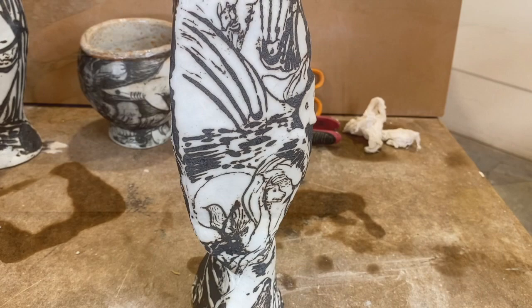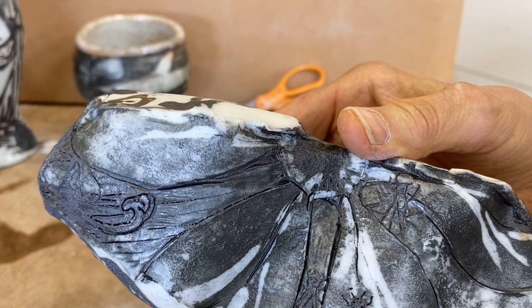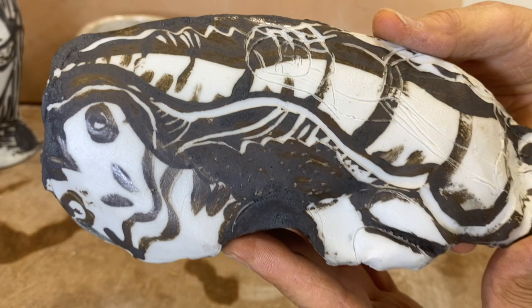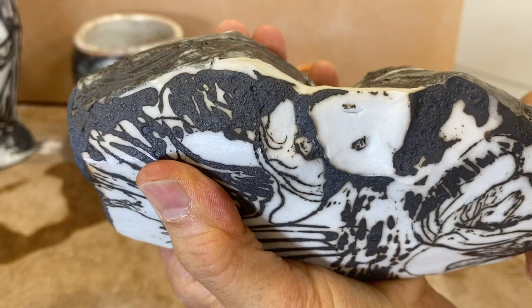For a change of pace — remember we used low-fire black slip. Here it is on the tarp paper piece, a three-sided piece. This is it thinned down and brushed on — I think it's pretty, I like it. Then here it is in the inlay where it's much thicker, and it's bubbling and blistering and boiling. On this side, brushed and cut through and a little bit thicker — I like it. But it's maybe not the best thing to use for inlay, because the inlay gets kind of bloated and unclear. It's not as crisp and sharp as it could be.